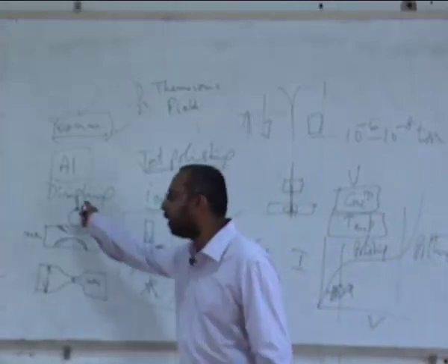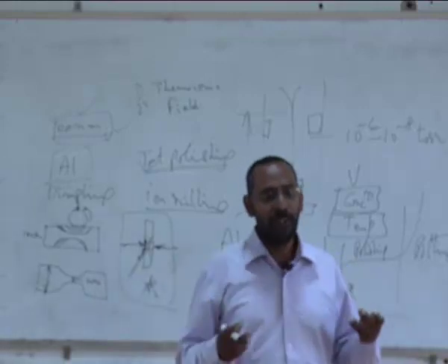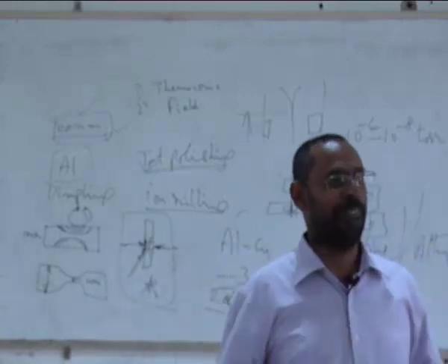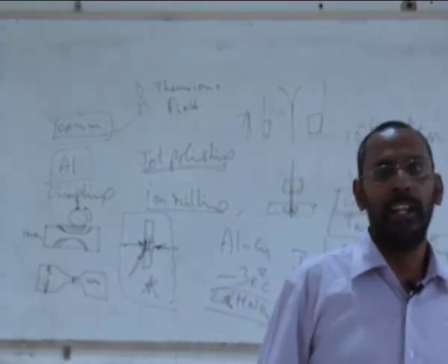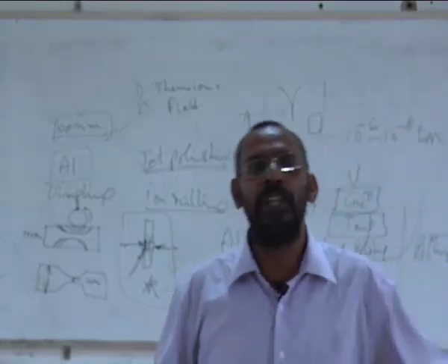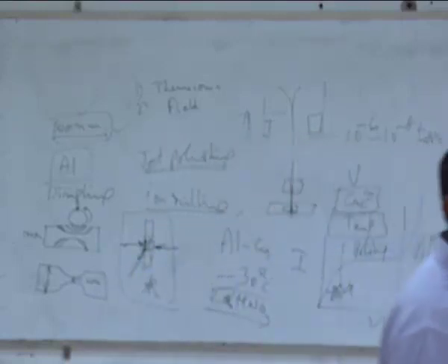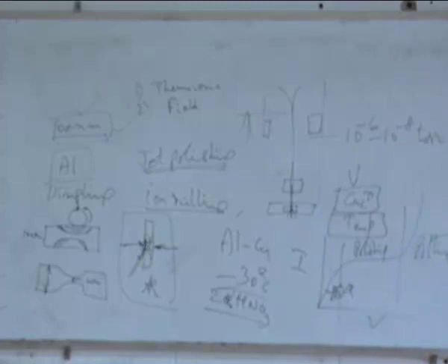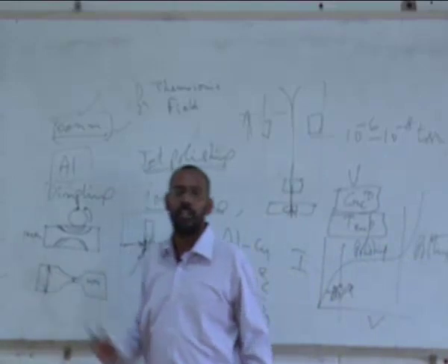Before ion milling, we have to do dimpling. But in all this process you are grinding the sample, so there is a possibility of certain deformation. Luckily, ceramics do not get deformed easily. You don't create dislocations in ceramics, because ceramics are very high melting materials. So there is not much plastic deformation in ceramics. Ceramics are all brittle, right? So as a result, that problem may not be there in ceramics like this.